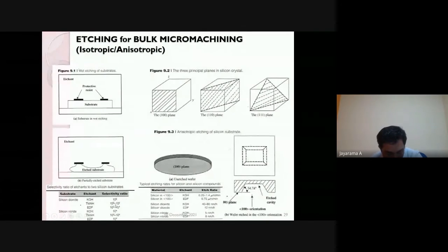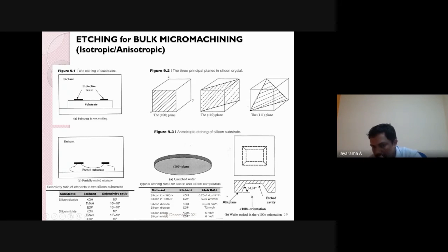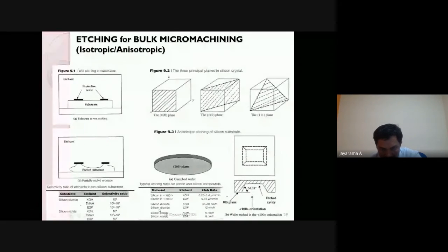Selectivity ratio is 10 cube. TMAH, EDP - these are different etchants, and their selectivity ratios are different. Typical etching rates of silicon and silicon compounds depend upon the type of plane. For the 100 plane, KOH etch rate is different. If you use silicon 100 plane with EDP as etchant, the etch rate is 0.75 micrometer per minute. For silicon dioxide, SiO2, KOH etch rate is 40 to 80 nanometer - that is the etch rate.